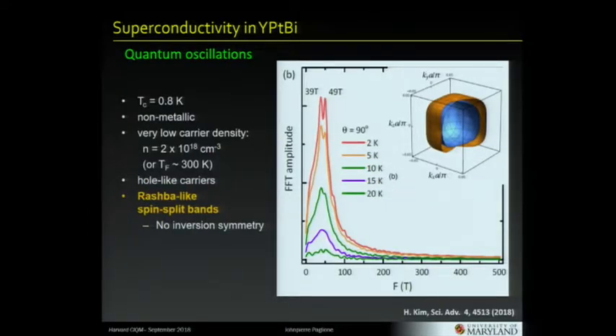Here's a snapshot of the quantum oscillations work we did, just showing the Fourier transform of the data to make it simple. But it's pretty simple. There's essentially one frequency, or a nearly spherical Fermi surface, that's split due to the lack of inversion symmetry. So there's two spin-split bands, or surfaces, I should say, shown right here, so blue and orange. One is spin up, one is spin down, if you want. And you can see that the splitting right here is of the order of 10 Tesla for a roughly 50 Tesla frequency. So it's quite large. So that's an indication of the strength of the spin-orbit coupling.